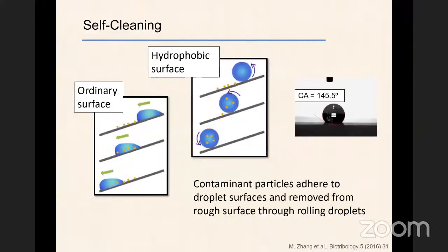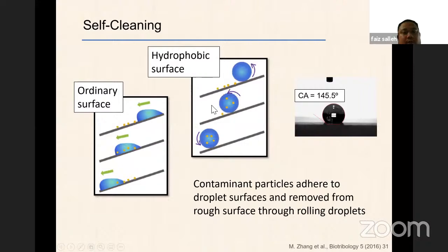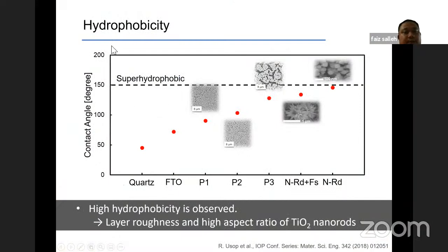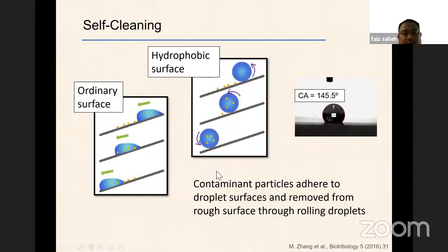So for the first one, the ability to repel water for that smart window, we are using the hydrophobic surface in order to collect all the contaminant particles in front of the window and to remove them from the rough surface through rolling droplets. So if we plot the contact angle measurement, we compare the materials: we compare the quartz, we compare the FTO, and then we compare the porous TiO2 layer, which was fabricated by using the spray pyrolysis deposition technique.